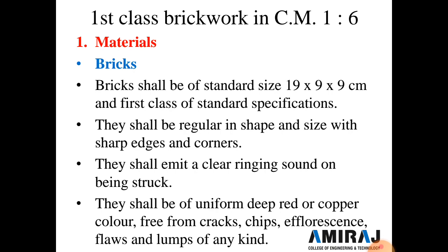So for brick, in first class brickwork we use the standard size of brick, 19 by 9 by 9 centimeter, which is the first class standard specification, and they shall be of regular size and shape with sharp edges and corners. And when we strike two bricks against each other, we hear a clear ringing sound, and they shall be uniformly deep red or copper in color, and free from cracks, chips, efflorescence, flaws, and lumps of any kind.